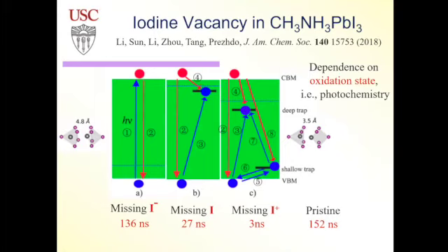Now about chemistry. If you have a semiconductor, silicon, you start sending current, the structure will not change. If you have an inorganic quantum dot, you photoexcite, the structure will not change. But if you shine light on a molecule, the structure can change. The same can happen here. If you have a vacancy, right? So now it's a vacancy. In the stable state, with no extra charge, no light shone, you have no mid-gap trap state. But if you shine light or you send charges and the charges can be trapped, you create new chemical species.